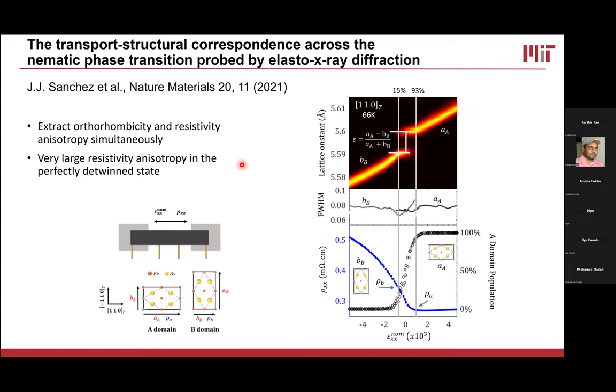So what kinds of information can we get out from this kind of measurement? If I go to a fixed temperature and I apply strain and I do these X-ray diffraction cuts, then I can get data about how the transport is related to the lattice constants and the domain structure. So first off, I can define the orthorhombicity just from the splitting between the two lattice constants at the zero strain point. So that gives me my structural anisotropy. Then by applying strain, I can switch between the perfectly detwinned A domain and the perfectly detwinned B domain. So that gives me access to the resistivity along the A direction and the B direction. So those points are marked here.